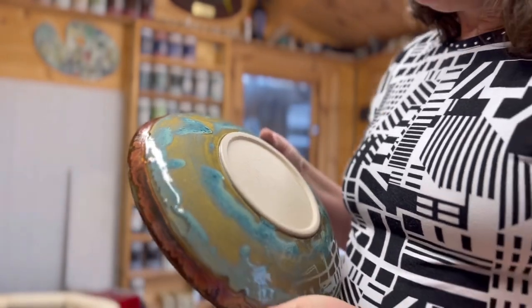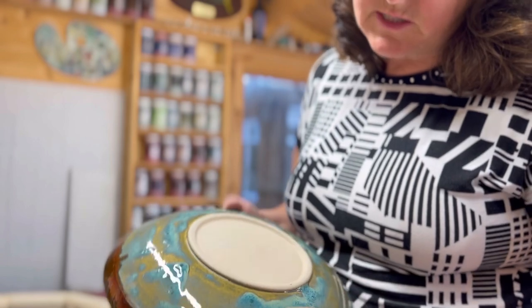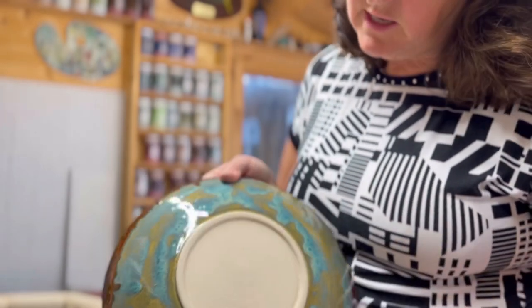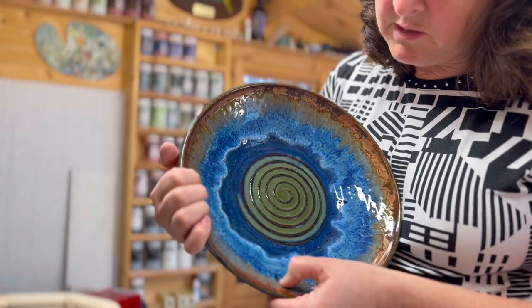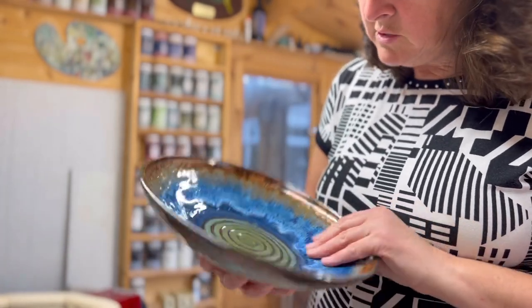Now, the conversation in the past had been about my dirty hands, whether glaze slips, because, you know, it's slipping because it's not adhering to the clay. And as you can see, it really has slipped there. I also have a lot of pinholes, which to me can be the dirt, and maybe the kiln too hot. I haven't got pinholes in the middle with the textured turquoise. I have got pinholes around this band here.